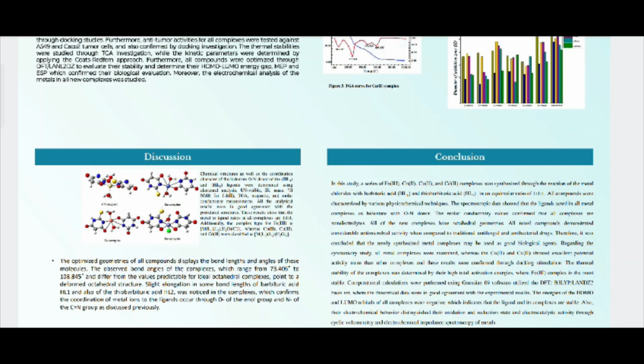Regarding the cytotoxicity study, the cobalt and the copper complexes showed excellent potential activity, more than other complexes, and these results were confirmed through docking simulation. The thermal stability of the complexes was determined by their high total activation energies, where the iron complex is the most stable. The energies of the HOMO and LUMO orbitals of all complexes were negative, which indicates that the ligand and its metal complexes are stable. Also, their electrochemical behavior distinguishes their oxidation and reduction states and electrocatalytic activity through cyclic voltammetry and electrochemical impedance spectroscopy of metals. Thank you for all.